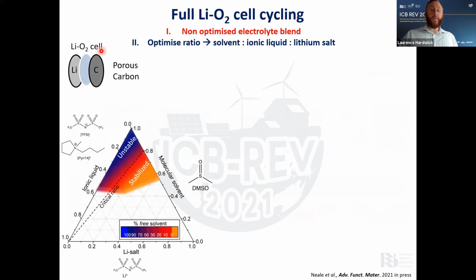So now we have our optimized electrolyte for the lithium side, and what we did then was to test this against a porous carbon in a full lithium oxygen cell. This shows all the different compositions we investigated, and we used spectroscopy to understand where the critical ratio is, where all the dimethyl sulfoxide is lithium coordinated, and this stabilizes our dimethyl sulfoxide. We looked at two blends within this region here, a non-optimized and an optimized blend.